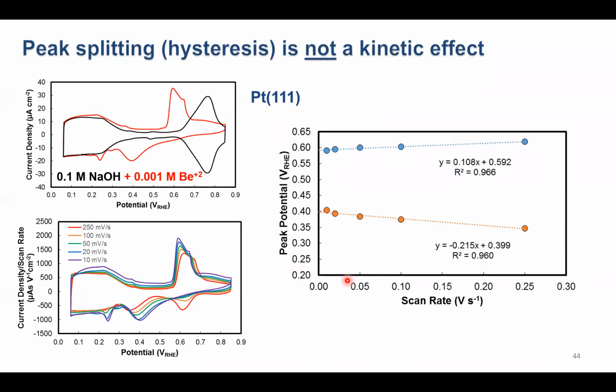And that's maybe a little bit easier to see if I plot the potential of the peak. So the blue points are the potential of the peak in the positive going scan. The orange are the points in the negative going scan. And what we can see is that they do show a slight dependence on scan rate, but it's not large. And these two lines do not intersect. If really this was only a kinetic effect, these two peaks at the slowest scan rate should be at the same potential, and these two lines would intersect at the same potential. And you can see that they don't.